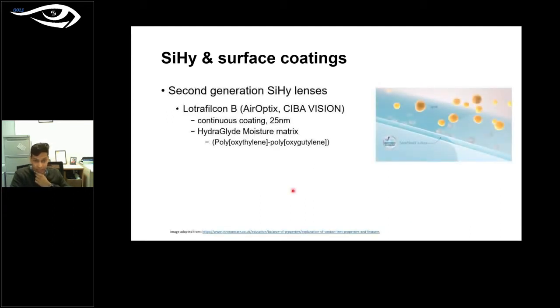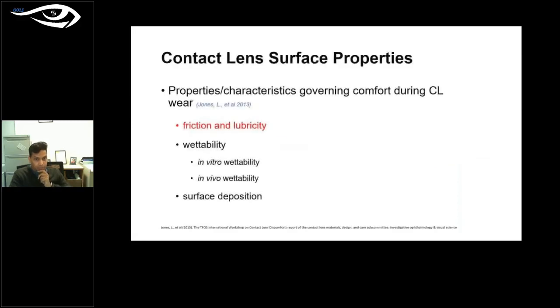Okay, so then there are second generation silicone hydrogel lenses. The example that I am taking in my talk is Lotrafilcon B. The important modification between Lotrafilcon A and Lotrafilcon B is the injection of HydraGlyde, a moisture matrix, which is incorporated within the lens, sorry, not the matrix, but on the surface. Apart from the lens coating, what we also have is a HydraGlyde moisture matrix. So this will render comfort for 2 reasons. One is the coating, and also we have moisture incorporated within the lens material. So let's look at how these different lenses will perform in terms of friction and lubricity.